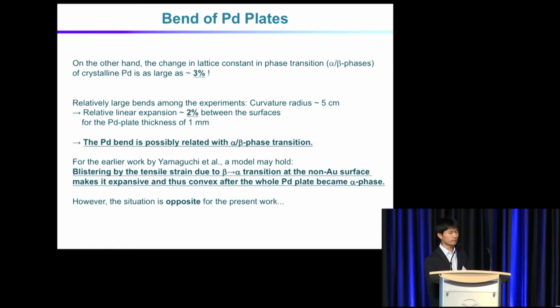On the other hand, the change in the lattice constant, as I mentioned a little bit before, in the phase transition was as large as 3%. And from the curvature of the bent sample, we estimated a relative expansion of about 2%, although we had some variance for the bent situation, so not quite reproducible. But probably the bend is related to the phase transition.